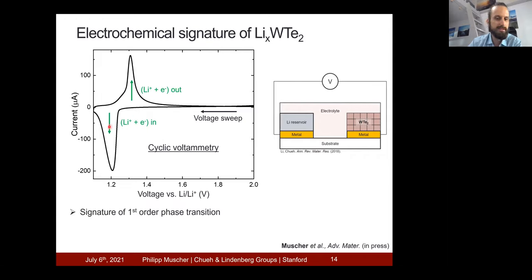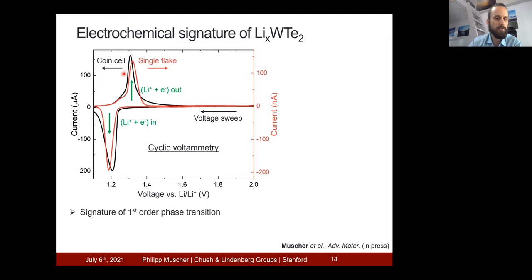So these peaks in cyclic voltammetry are a signature of a first order phase transition. So the data that I've shown you is actually from a coin cell where we look at bulk tungsten ditelluride, so many, many particles to get the electrochemical signature. However, I can look as well at single flakes of tungsten ditelluride on the platform that I showed you before. And actually the signature is exactly the same, albeit the currents that we measure are 1,000 times lower. So this demonstrates that we have single flake electrochemical control over the ion insertion and also reversibility.